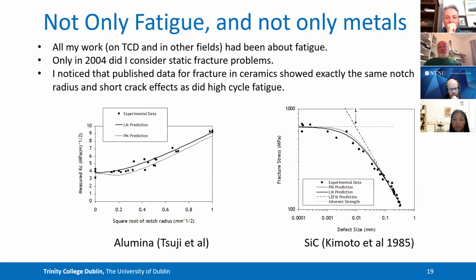But anyway, it's a fact that if you look at the ceramics results of the fracture, not the fatigue, but the fracture of ceramics, and you look at the effect of notch radius on the left-hand side here, or you look at the effect of the length of the defect or crack on this graph on the right, then you see dependencies, you see behavior which is exactly the same as you see in fatigue.